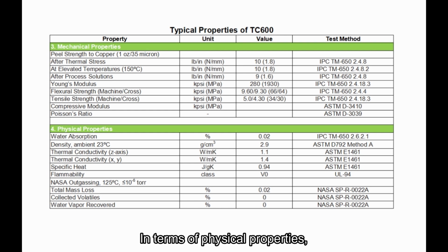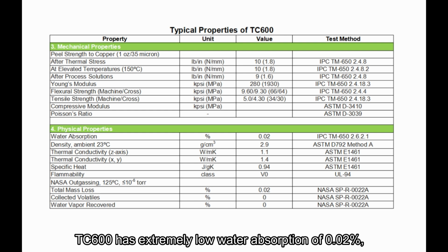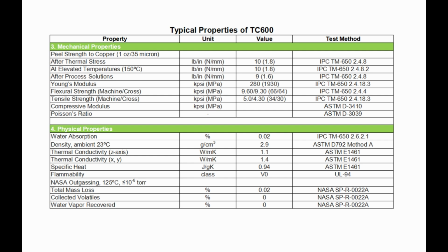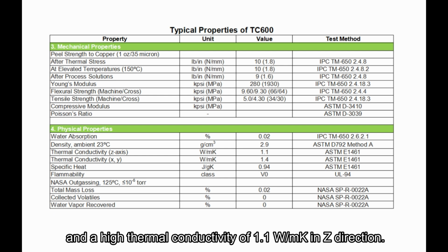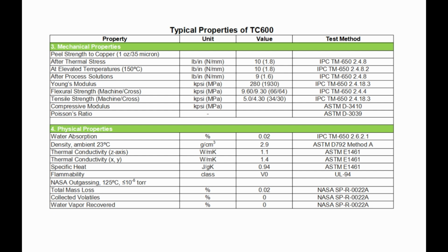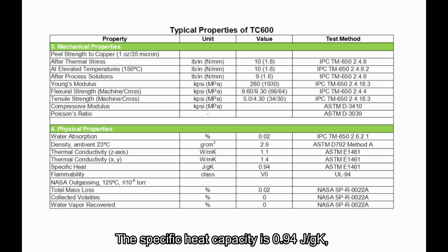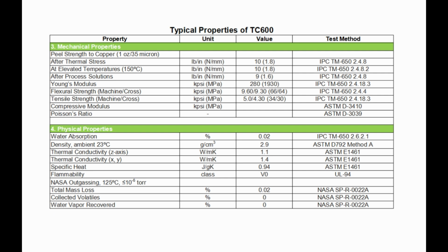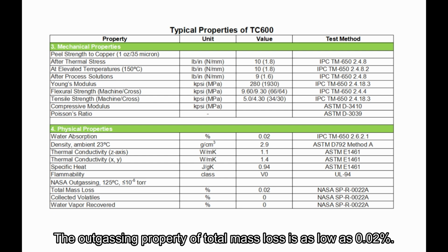In terms of physical properties, TC600 has extremely low water absorption of 0.02%, with a density of 2.9 grams per cubic centimeter and a high thermal conductivity of 1.1 watts per meter per Kelvin in Z direction. The specific heat capacity is 0.94 joule per gram per Kelvin, and it has a UL 94 V-0 flammability rating. The outgassing property of total mass loss is as low as 0.02%.